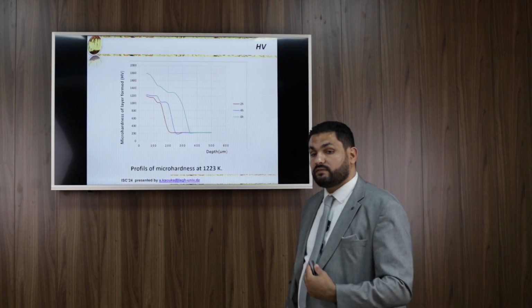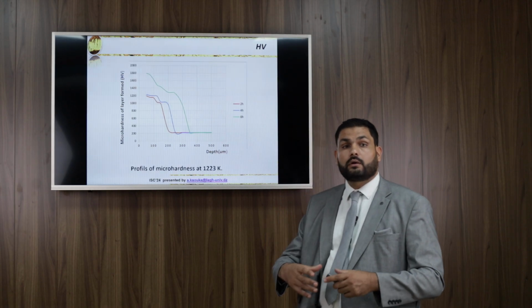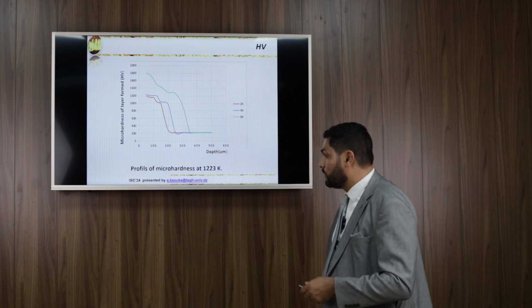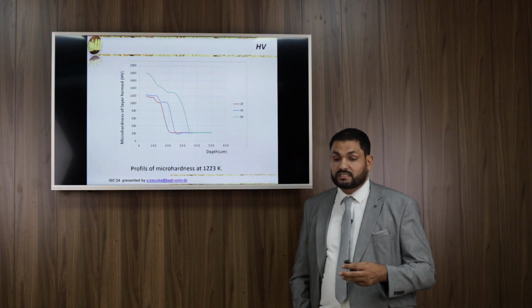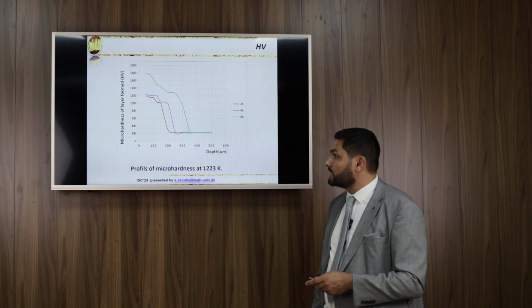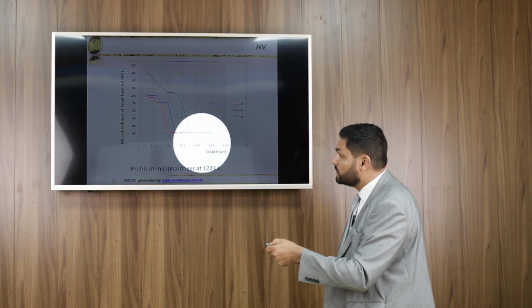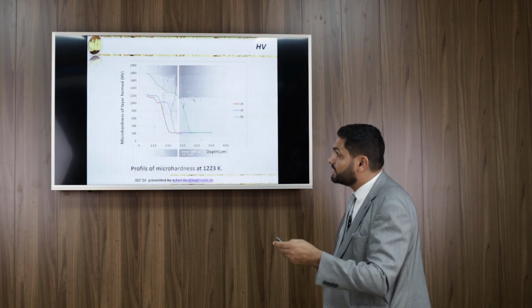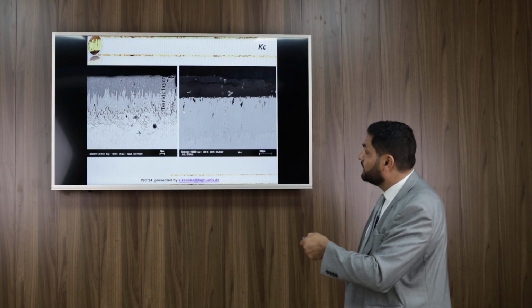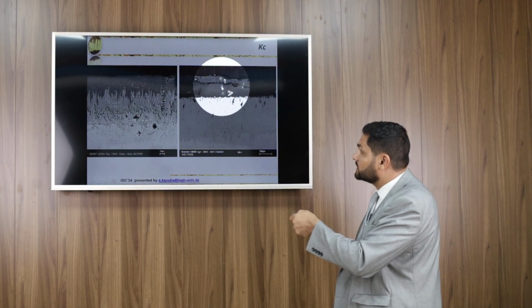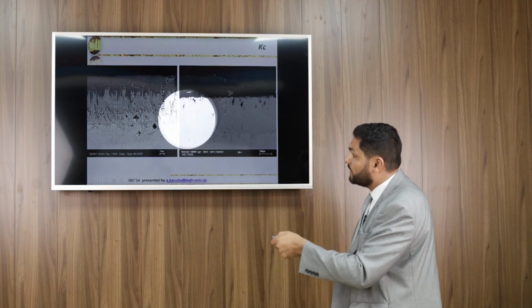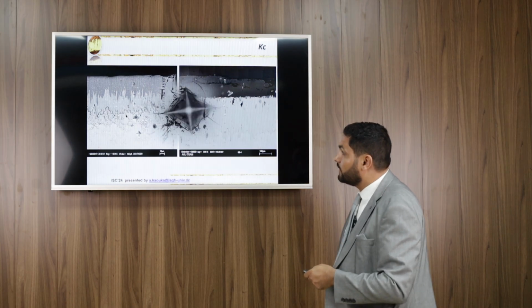And after that, we draw the curve of profiles of micro hardness as a function of depth of boride layers, and we have an increase with boriding. This is here in the surface, and here in the substrate. So it's constant here, because we have an increase of boride layers. As you see here, this is the Vickers indentation as a function of the depth, and we found our results.